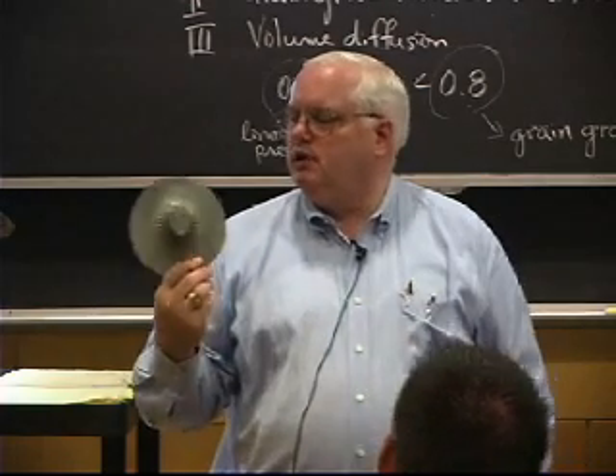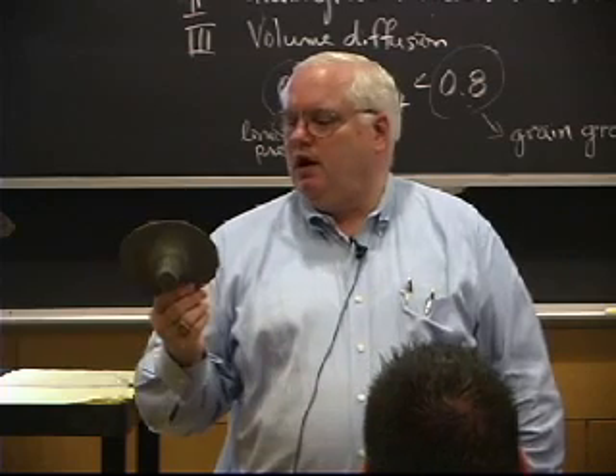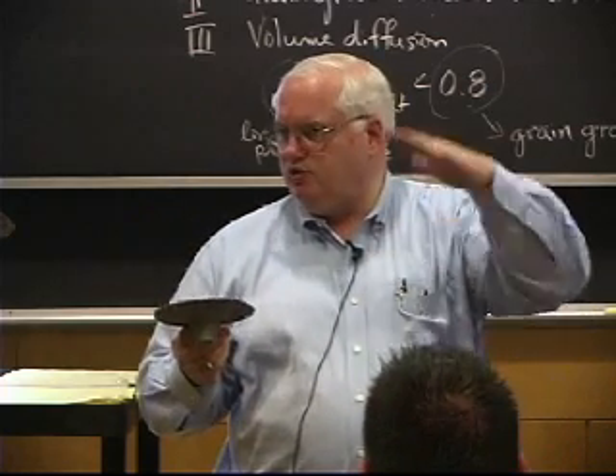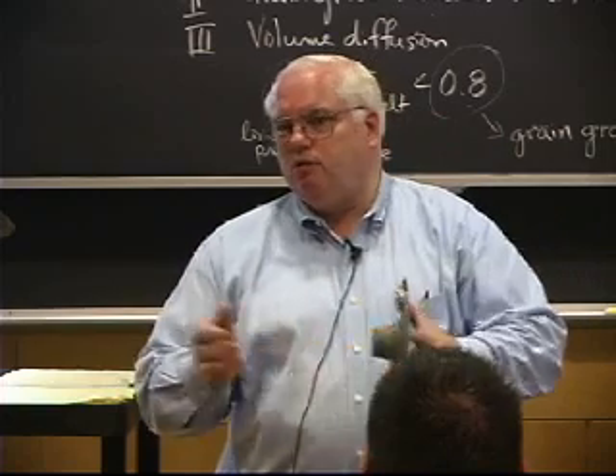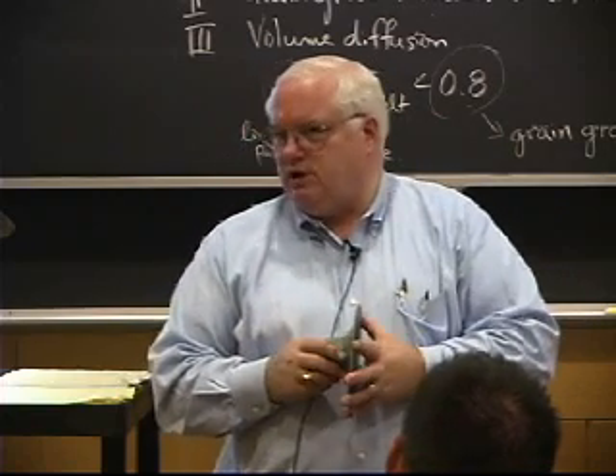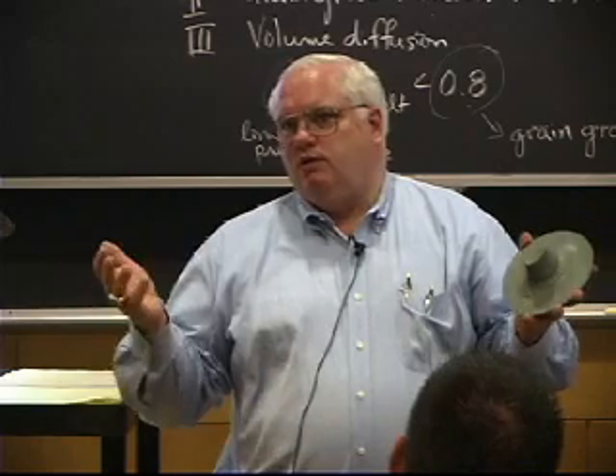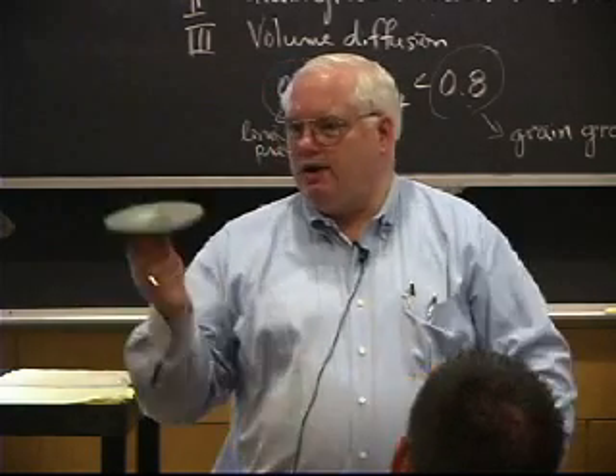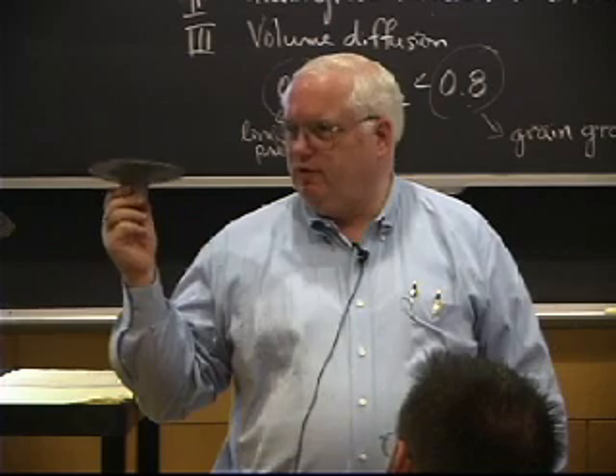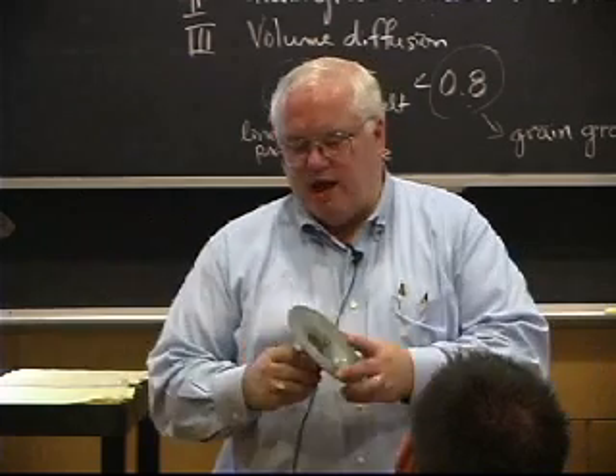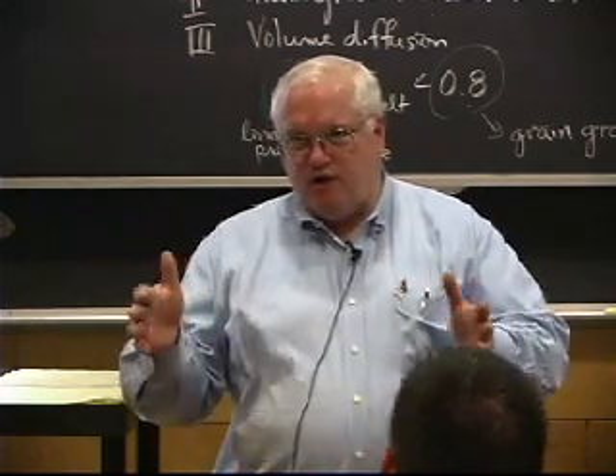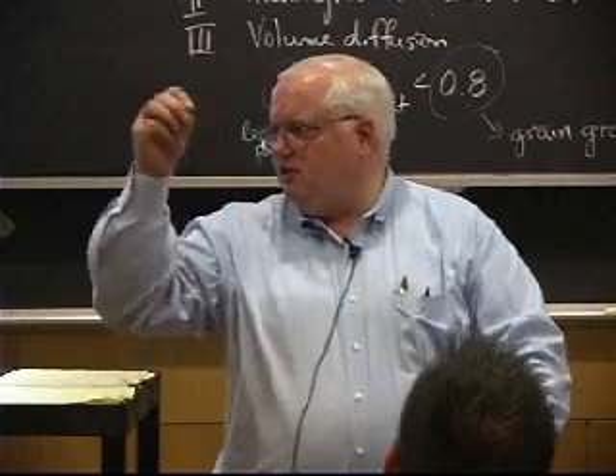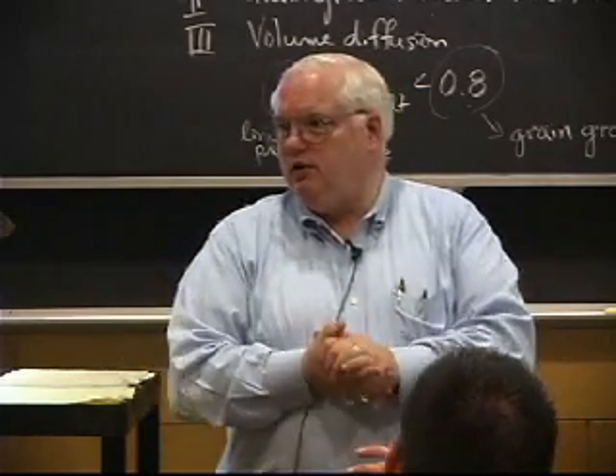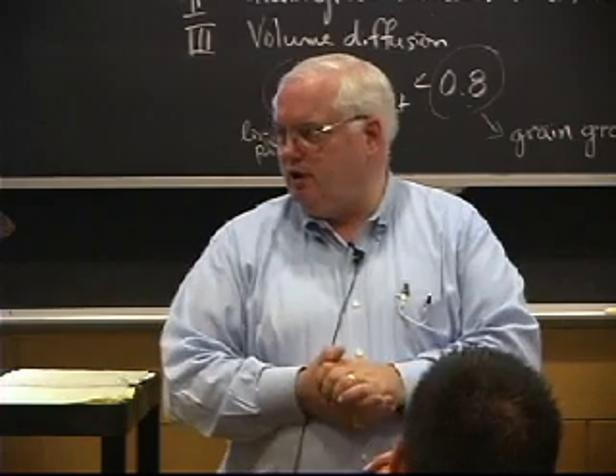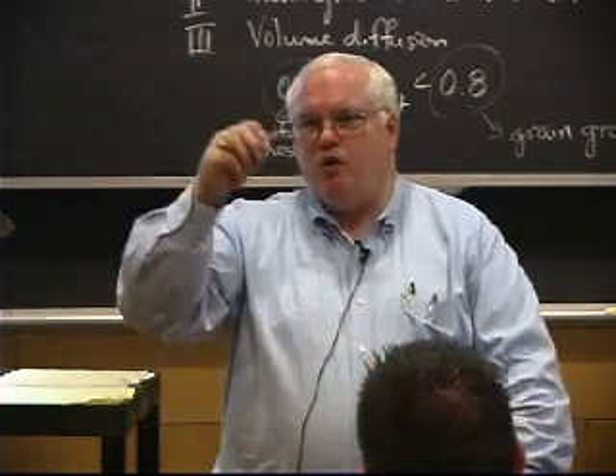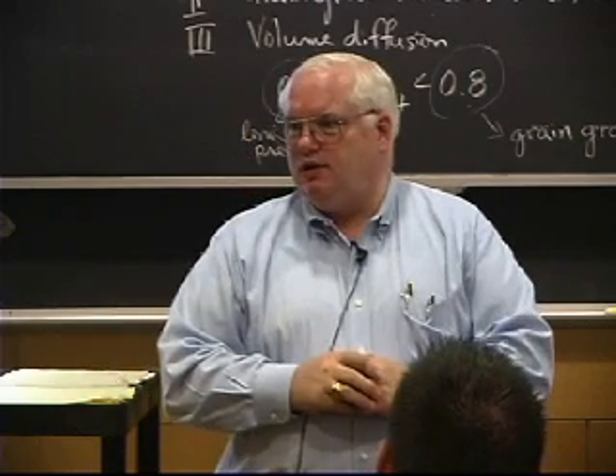This happens to be an aluminum zinc alloy, and it goes through a solid state phase transformation too, so you can get very, very fine grain size. Typical grain sizes in processed metals might be anywhere from 20 to 200 microns. We're talking about getting down to 1 to 5 microns, very, very fine grains, to get something that's superplastic. And what Backofen found is that as he got finer and finer grains, the ductility in a tensile test went up. Typical ductility in a tensile test might be 30%, 40%, 50%. Well, when you get very fine grains, you can get 400%, 800% stretch in a tensile test.